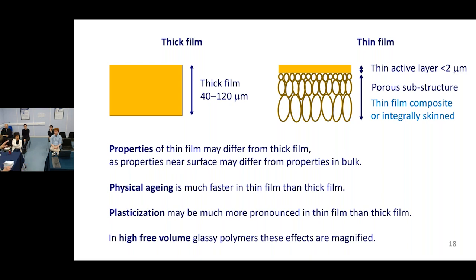So something which, in a thick film, looks like it can easily be stable over a couple of years, those changes can occur in a month or less in a thin film. Plasticization can be much more pronounced in a thin film than a thick film. So something which doesn't show much effect in a thick film can show a very pronounced effect in a thin film. And on top of that, we're trying to work with polymers which are as permeable as possible.